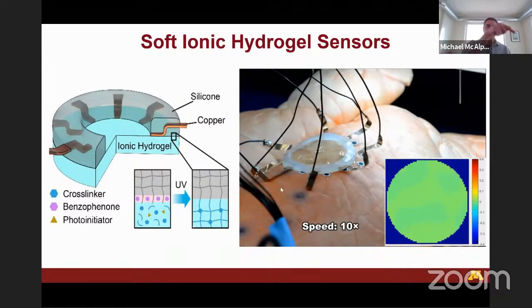And the idea here is you place electrodes around the circumference of the device. And so this way, instead of having to print multiple sensors as an array, by printing the electrodes on the circumference and then doing some clever voltage, it's basically like a voltage divider. As you scan the electrodes on the circumference, you can basically create a pseudo array which doesn't actually exist on the interior of the structure, and basically map out the deformations.